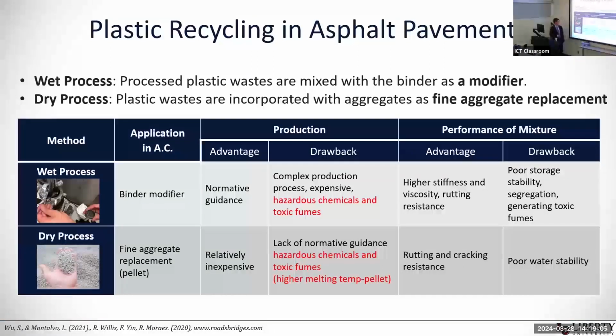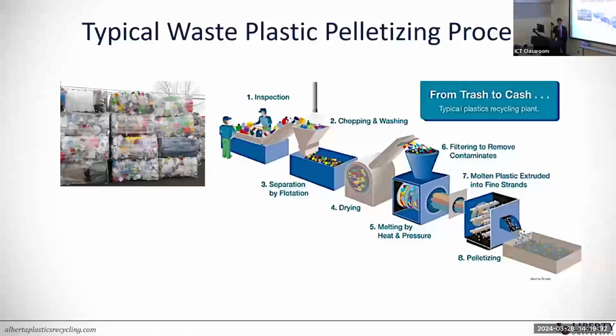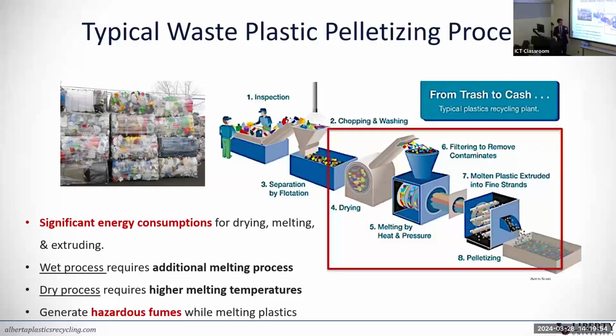As I explained earlier, we have two different types of process to recycle plastic. But the common drawback of the post-process of the recycled plastic is that it produces hazardous chemicals and toxic fumes, especially when you melt it and make the pellets to be used in the production of the asphalt materials. The typical pelletizing process starts with collection, inspection, chopping, separation, drying, and then melting with heat and pressure, and then the molten material goes through to make the pellets. The problem is these steps require a lot of energy consumption, and because it's melting the plastic at a higher temperature, it emits fumes.